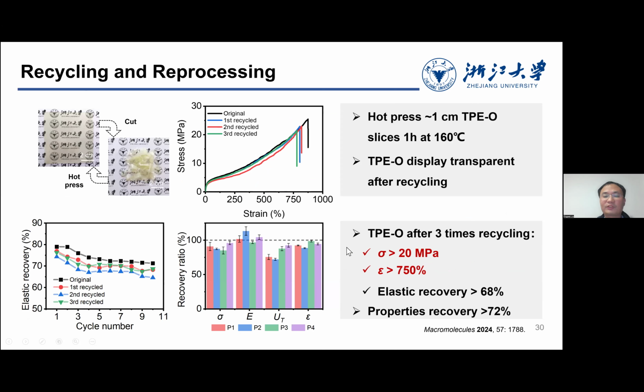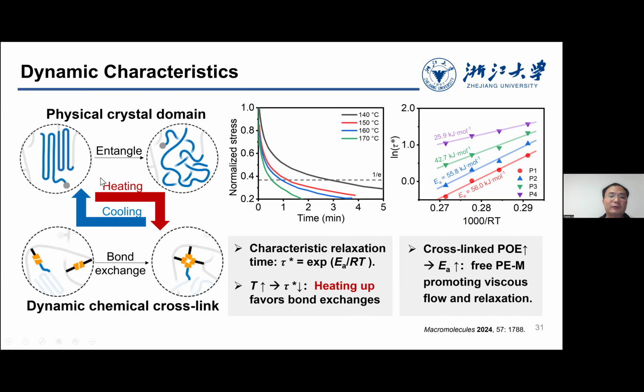So this kind of performance is all based on the synergy between the crystallization and also the dynamic chemical cross-linking. You can see here, if you heat it up, there is a melting of the crystallization part, and also the dynamic chain will be exchanged, and it has a relaxation time. In this way, you can do the reprocessing, and we also did the calculation of this activation energy. And here you can see the activation energy is higher than the previous one we showed a few slides ago. The reason is we introduced this crystallization part. It limits the relaxation at high temperature.